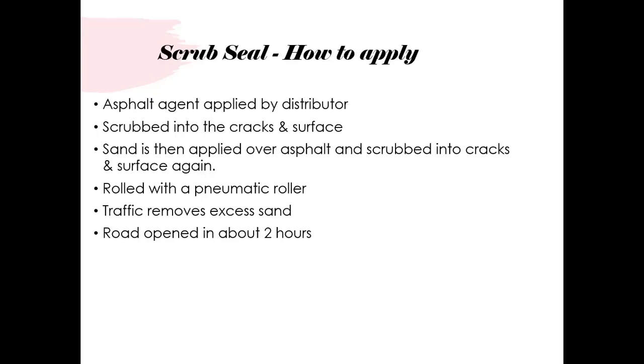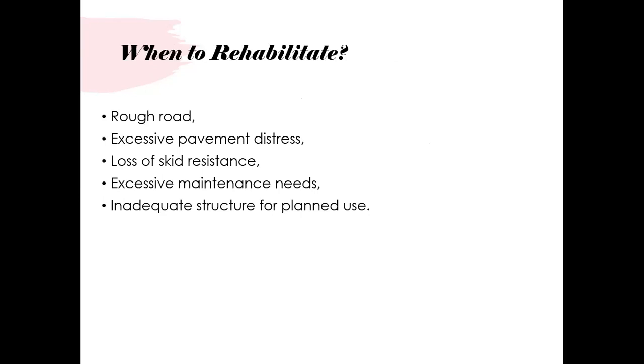So how to apply it: it is applied by a distributor. You have to scrub into the cracks. Sand is then applied. Roll with a pneumatic roller. Traffic removes excessive sand. The road opens in about 2 hours. That's why it is now being performed.